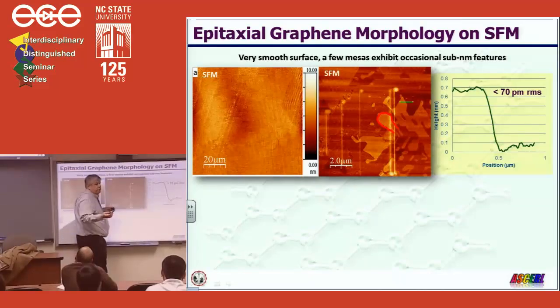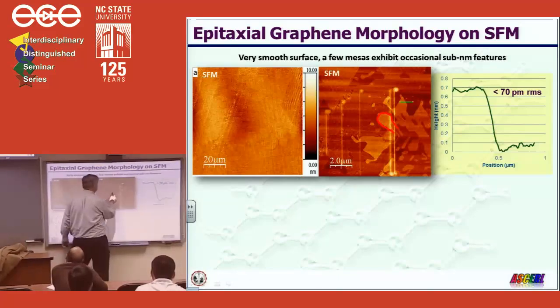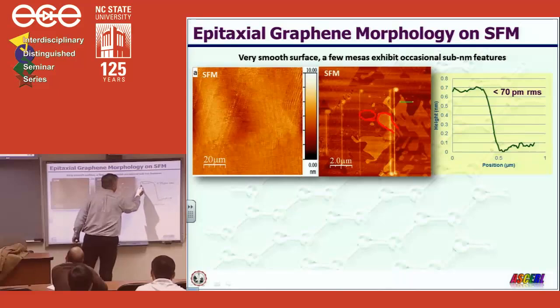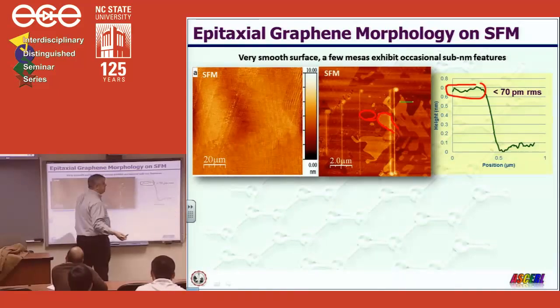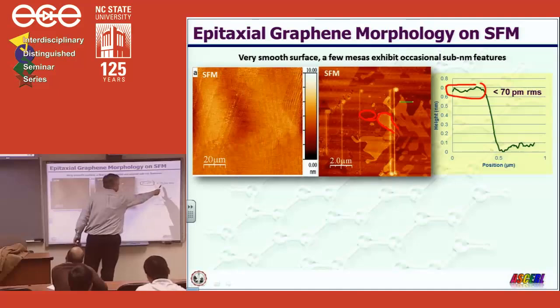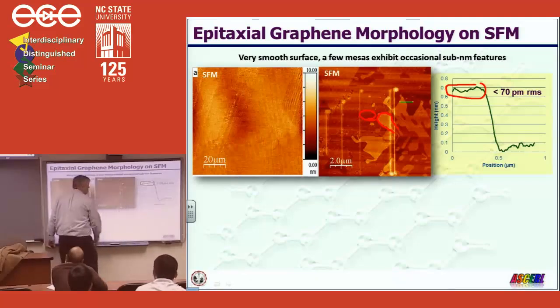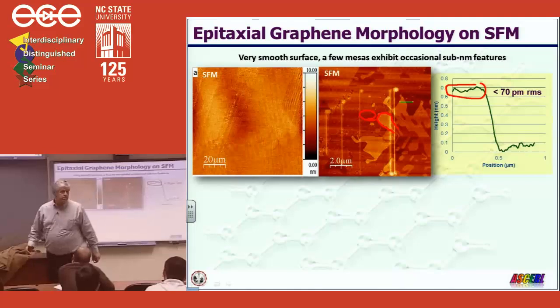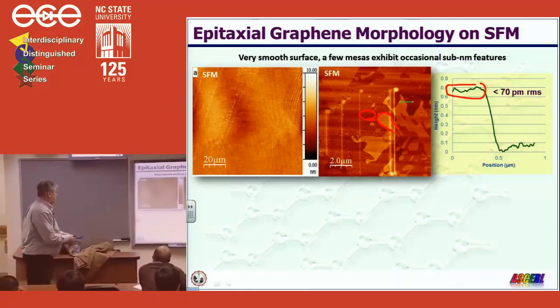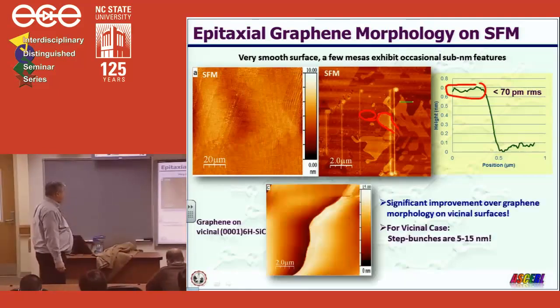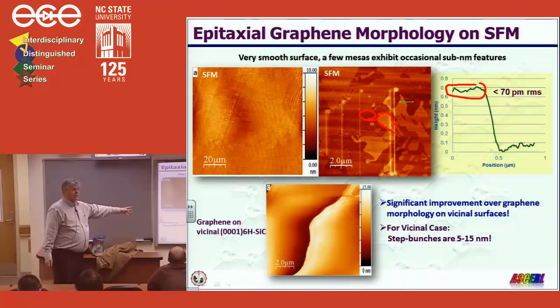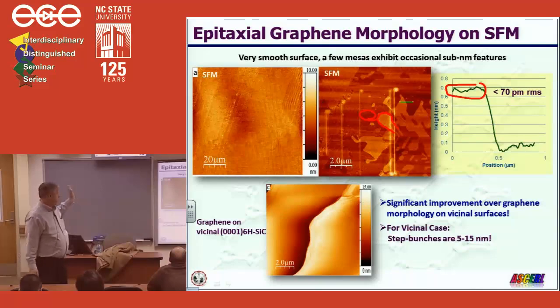It's just an imperfection. We don't know what causes it, and it only happens on a small number of the mesas. You get away from the imperfection, you look in this area, and it's relatively flat. And this is an ambient AFM, so it's instrument limited, and the roughness is 70 picometers. If I had a UHV AFM, I could probably drop it down an order of magnitude. So, it's very flat. Now remember, when we grew it on the conventional substrates, you get the step and terrace morphology, and the steps were 5 to 15 nanometers tall. So order of magnitude plus difference.